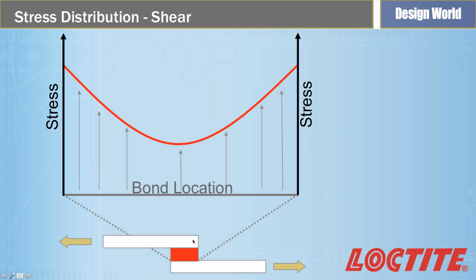This is a little different. Again, the white is the substrate, the red is the adhesive, but in this case, instead of applying a force vertically, we're pulling it side to side in shear. And as you can see, over that bond area, the stress is distributed across the whole area, but there are peaks at the leading edge and at the trailing edge. So, this is the next most aggressive stress, because you've created those slight stress concentrations at the leading edge. But there are things you can do, like increasing the width of your bond line that the force is applied to in order to maximize the ultimate strength.